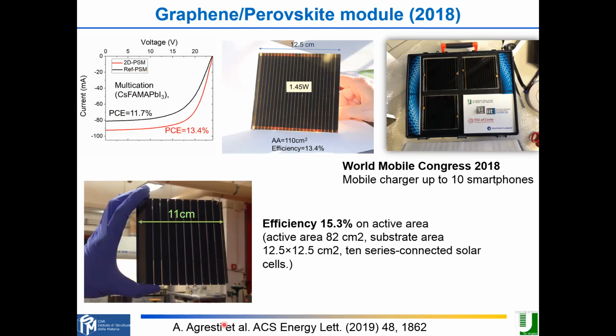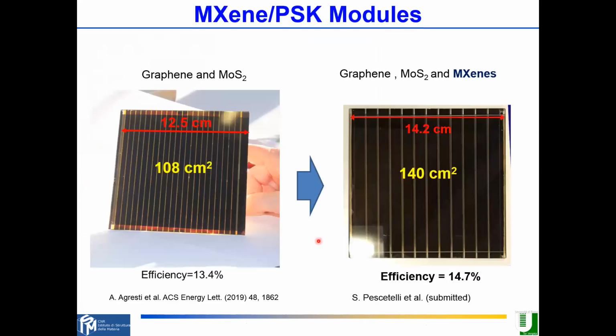So you can do some optimization. You can get 15.3% on a little bit smaller area. And nowadays, for example, we are even using the best optimization for a larger module, 140 centimeters square active area with an efficiency of 14.7%. So, I mean, is it possible to use this 2D strategy? It's quite compatible with a solution process printable technology. So it's very effective to improve efficiency and also stability, but I have no time to show